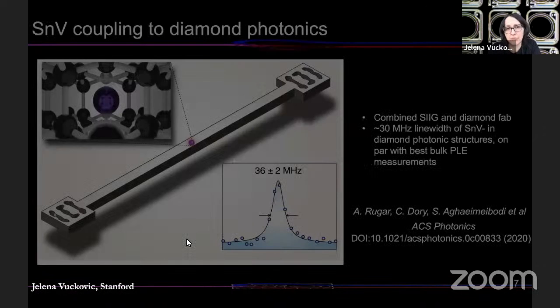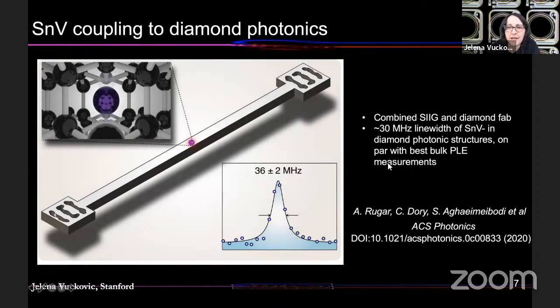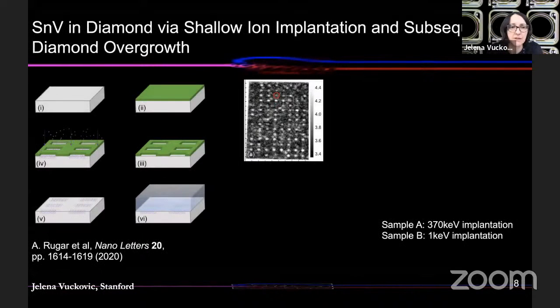And we have also very recently, a couple of months ago, demonstrated that we can even build optical structures, not just pillars to isolate single color centers, but actual optical devices around tin vacancies in diamond. And we can preserve very small linewidths of about 30 megahertz, which is comparable to linewidths inside of the bulk materials. So that's quite exciting. And we're scaling this up to more complex photonic structures and more color centers at the moment.